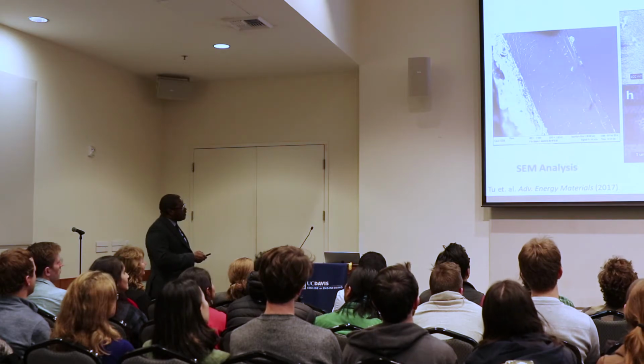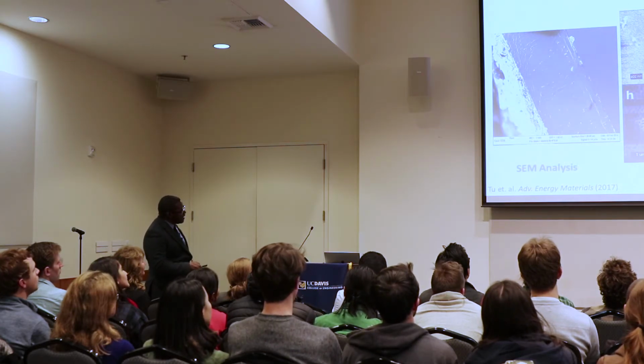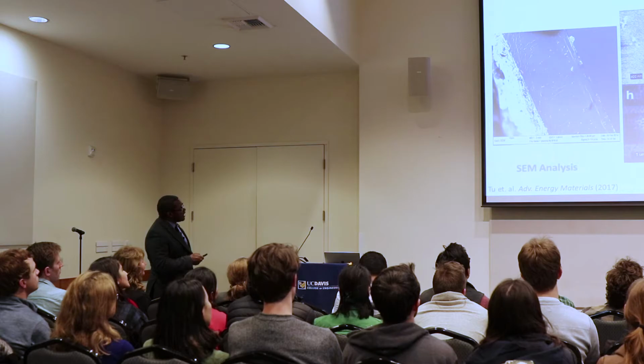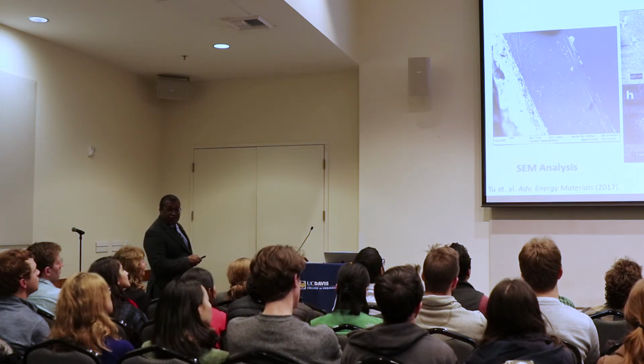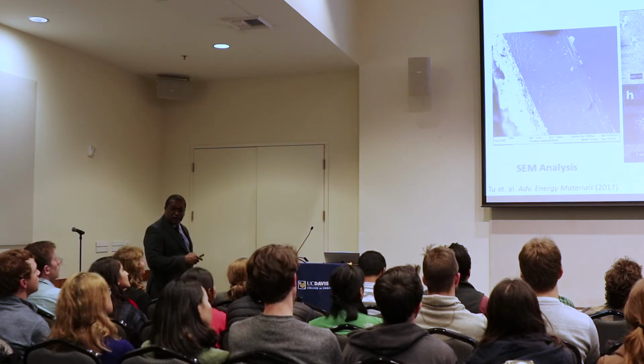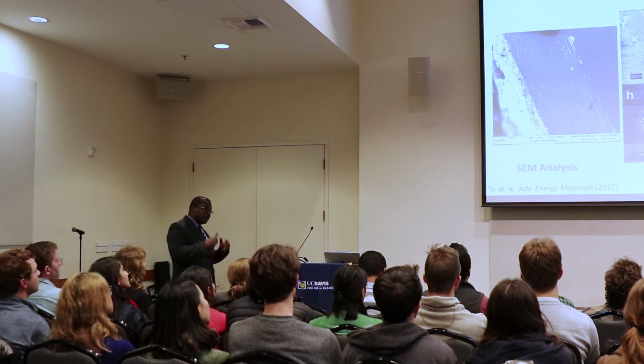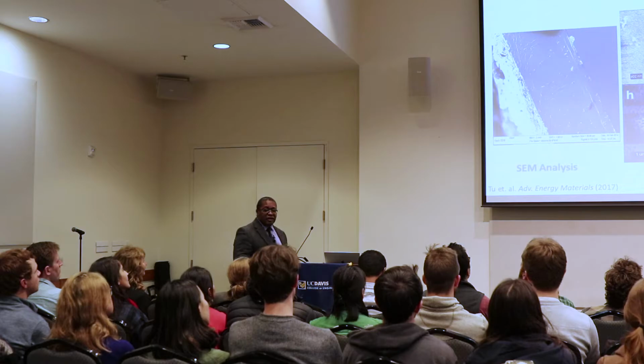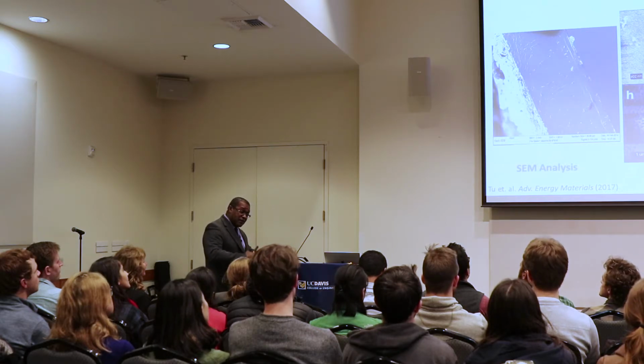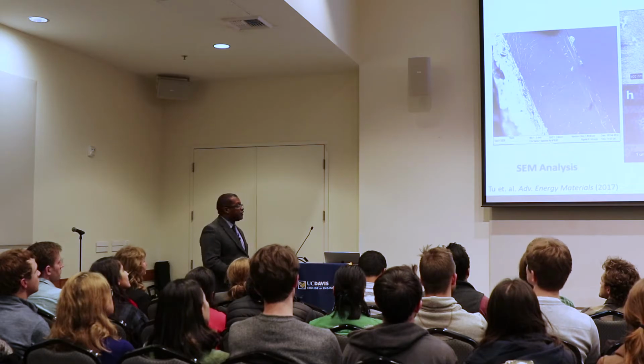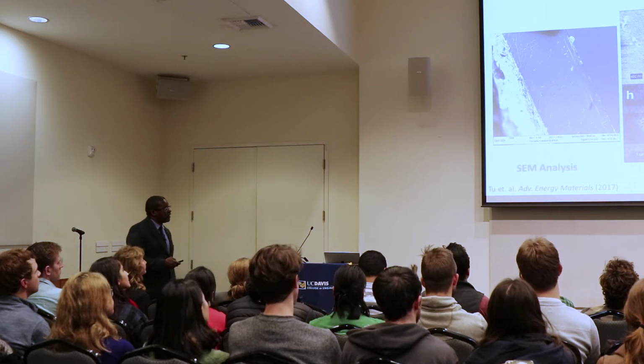So we basically looked first on a large length scale, and you can kind of see the sharp interface. This is lithium metal, this is the anodized alumina. You can see the sharpness of the interface after it's cycled, indicating, at least from the macroscopic scale, that the membrane just stops the penetration or growth at the interface with the lithium metal.